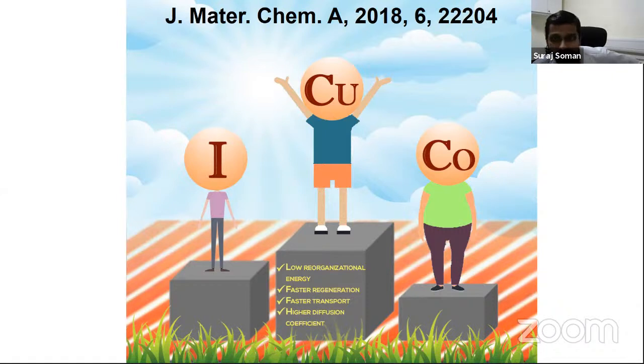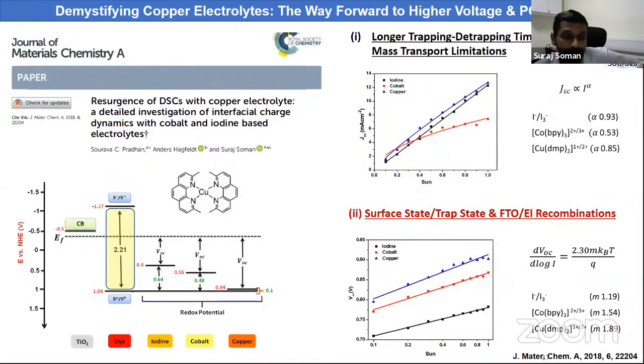So this is where we come back to our basic science, and we modified the electrolytes, where we can custom tune these molecules in a way to realize lower reorganizational energy between the oxidized and reduced species, and that led to faster regeneration, faster transport, and higher diffusion coefficients. This is a paper that we published in 2018, which is one of the seminal papers with this copper electrolyte system. And we went deeper into it, understanding what is actually the limiting process in these devices. We figured that there are certain trap state and surface state recombinations which can be addressed, and if we can do that, that can lead to much further improvement in the photovoltaic performance.